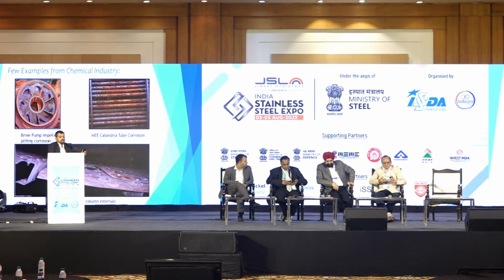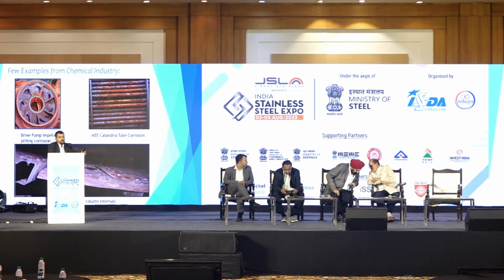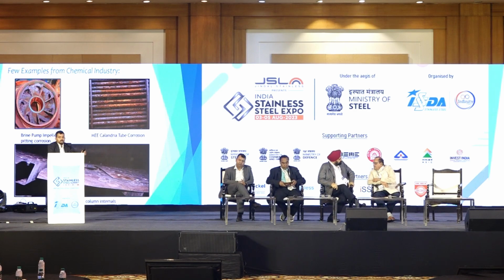Next is a distillation column where the service was a little foul. I would not say it is completely foul service, otherwise the material of construction would have been wrong. The initial thicknesses given by a column internals manufacturer are predominantly like 2 mm, and random packing thicknesses range from 0.3 mm. Within a span of 2 years, the packings and internals were worn out and we had to change them. Though the initial column MOC worked well, the internals were not of the same nature. We increased the thickness to 0.5 mm for the packing and 5 mm for the internals, and the life we are now getting is more than 5 years for these columns.